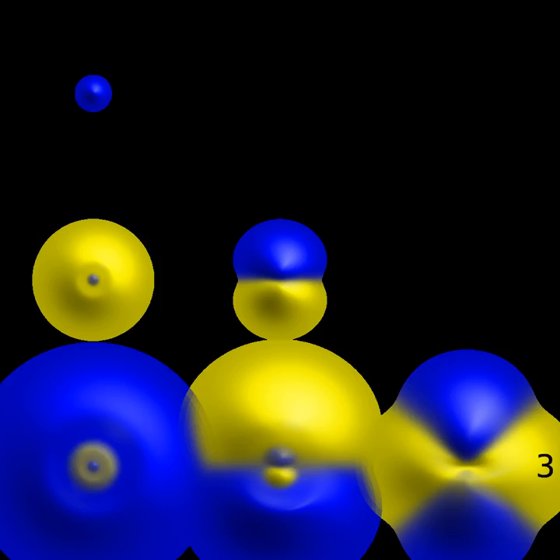The electron microscope directs a focused beam of electrons at a specimen. Some electrons change their properties, such as movement direction, angle, and relative phase and energy as the beam interacts with the material. Microscopists can record these changes in the electron beam to produce atomically resolved images of the material. In blue light, conventional optical microscopes have a diffraction limited resolution of about 200 nm. By comparison, electron microscopes are limited by the de Broglie wavelength of the electron. This wavelength, for example, is equal to 0.0037 nm for electrons accelerated across a 100,000 volt potential. The transmission electron aberration corrected microscope is capable of sub-0.05 nm resolution, which is more than enough to resolve individual atoms. This capability makes the electron microscope a useful laboratory instrument for high-resolution imaging.